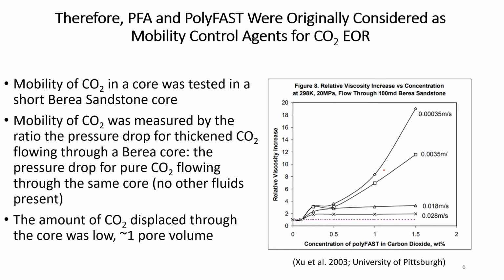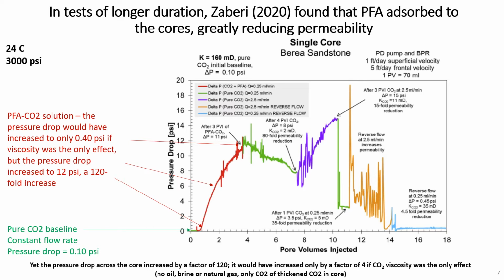Because of this, PFA and PolyFast solutions were tested for mobility control in sandstone cores. The initial tests were quite promising, getting up to 20 times viscosity increases in CO2. However, it was found that over longer times, PFA increased the pressure drop across the core greatly. Polymer had adsorbed onto the core walls, giving pressure drops 120 times higher than expected. This made mobility control unlikely to be viable, since we do not want to decrease the permeability of oil-producing formations.